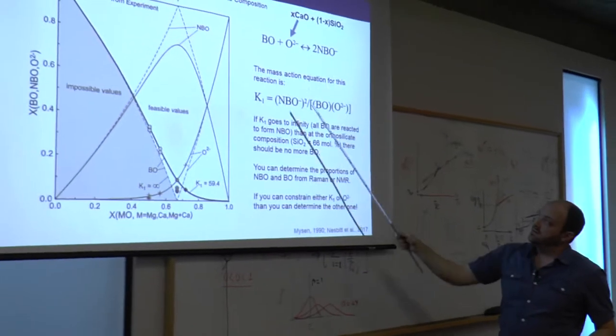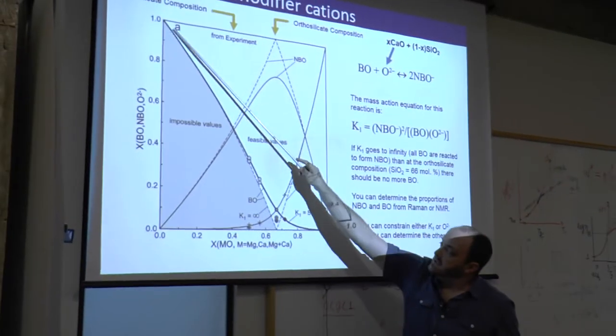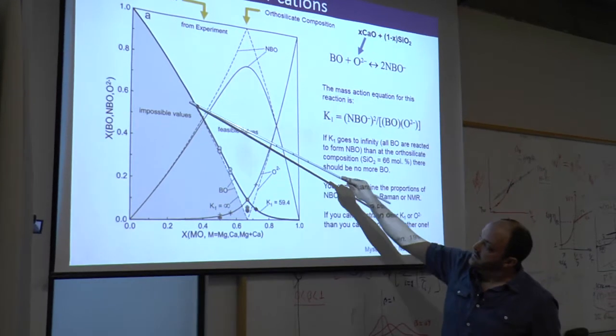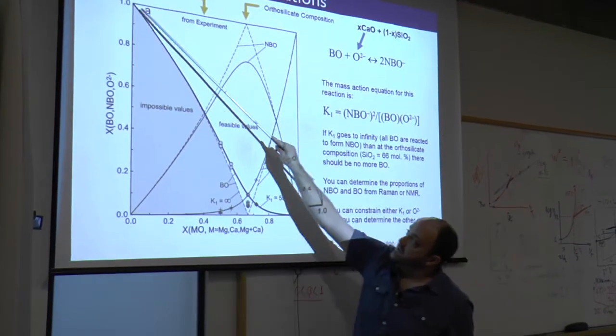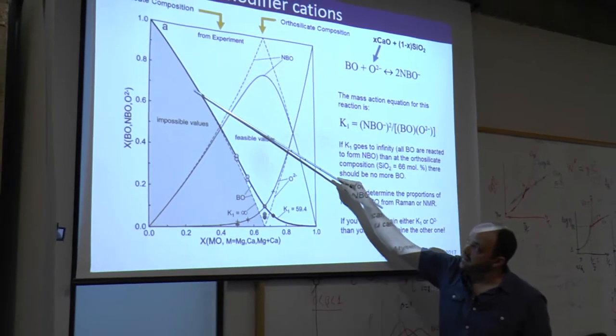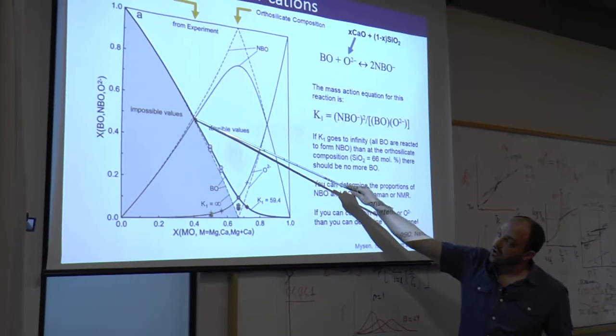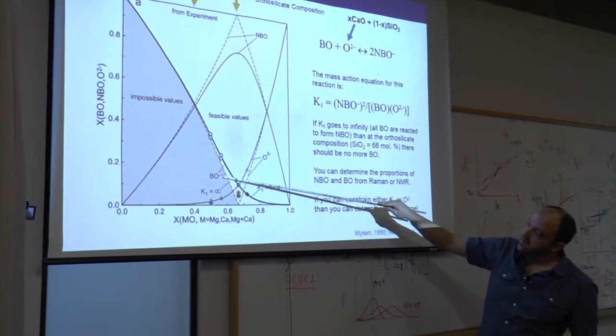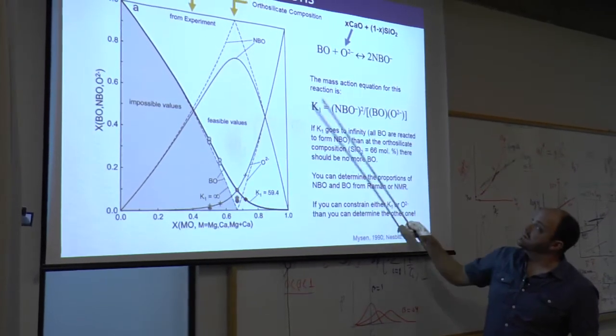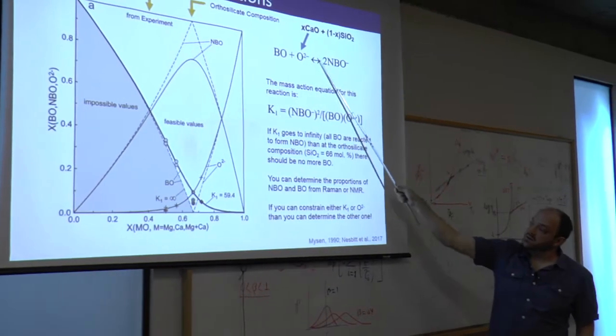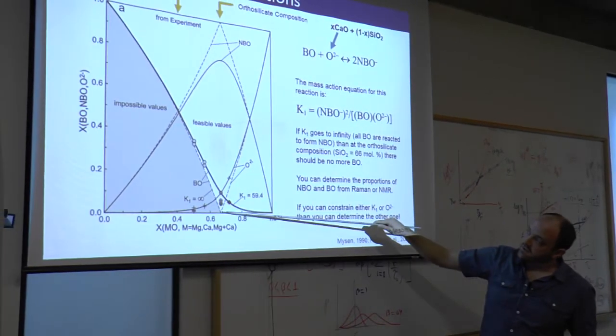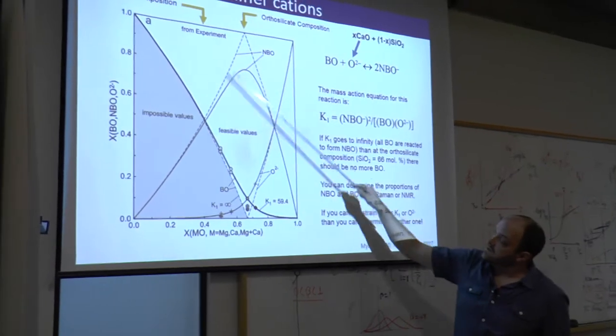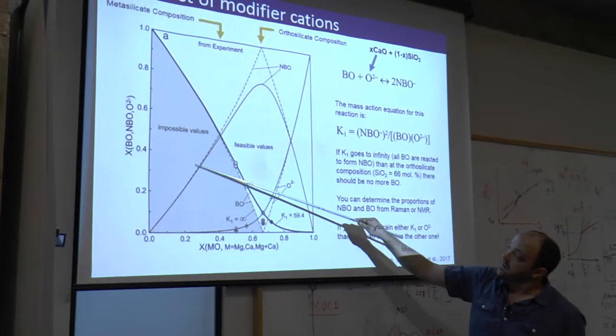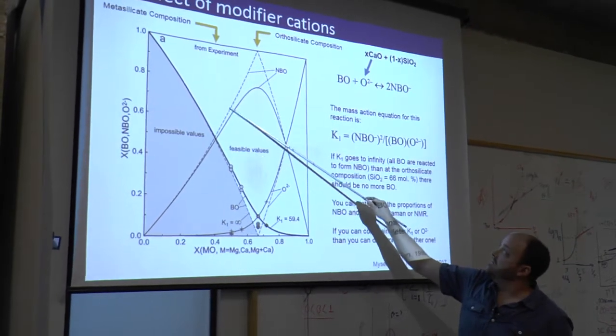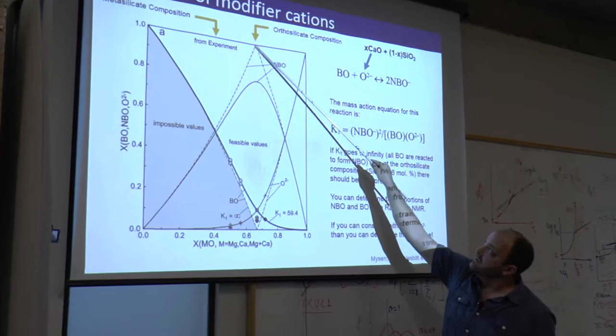A lot of people assume that this reaction goes to completion. As you increase the non-bridging oxygen, this is the bridging oxygen curve here. We have 100% bridging oxygen in pure silica. As you add modifier, the bridging oxygen should all be consumed and turned into non-bridging oxygen if this reaction goes to infinity. So if all of the modifiers are converted to NBOs, you will predict this curve here. As a consequence, the non-bridging oxygen starts off at 0. If all the modifier oxide turns into non-bridging oxygen, it will go to 100% at the orthosilicate composition.